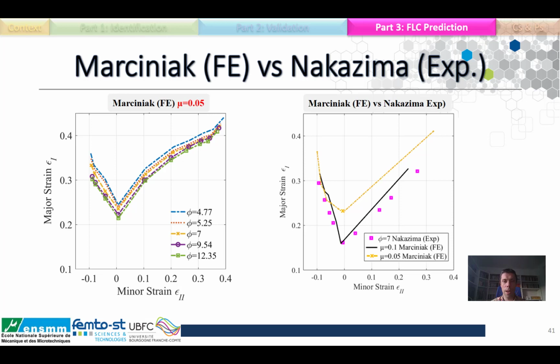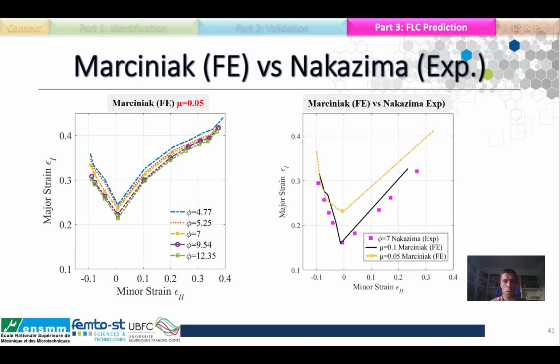That's why we tried another simulation with a higher friction coefficient, 0.1, and at that point you can see that the experimental curve and the simulation curve are in really good agreement. This result shows that we probably had some difficulty with friction during our experimental tests. This problem is well underlined by the fact that some specimens didn't break in the middle. It's often a sign of high friction.